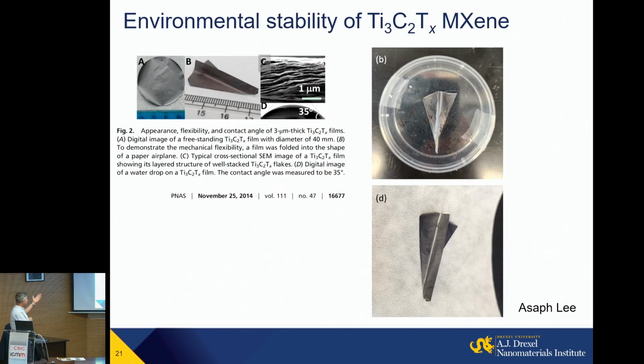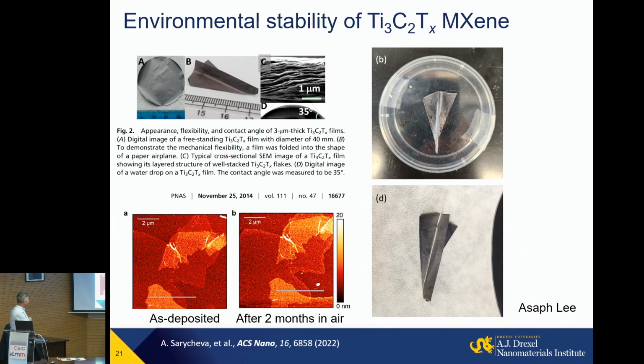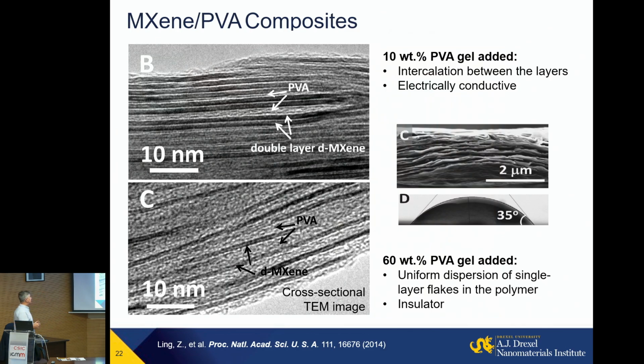And we know that, for example, this paper airplane was published in 2014. It is still intact, sitting in my office, and this is a 2 months old AFM film, remeasured in AFM, the same flake, and you see it really remains intact. So we can make this material sufficiently stable in air. This used to be a problem in the earlier days of MXene research. So again, they are ready for many applications.